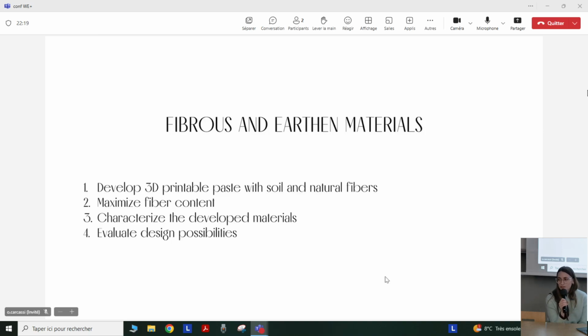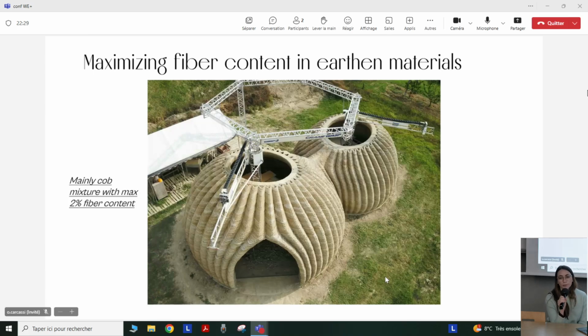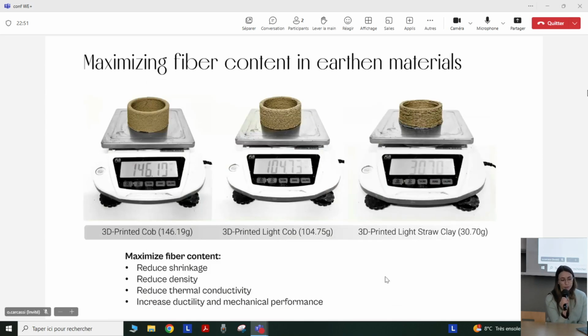But since this is a new research, we really had to characterize this new material and also evaluate the design possibilities. So where can we use this material? I don't want to bother you with the context, but if we look at the existing examples of 3D printed earth construction, they mostly use a recipe, a mix design, that is similar to a cob mixture. And in a cob mixture, you have around 2% of fiber content in mass. What we were able to achieve with our research, starting with a mix design that is similar to cob, so from 2% of fiber content, was up to 13% of fiber content.